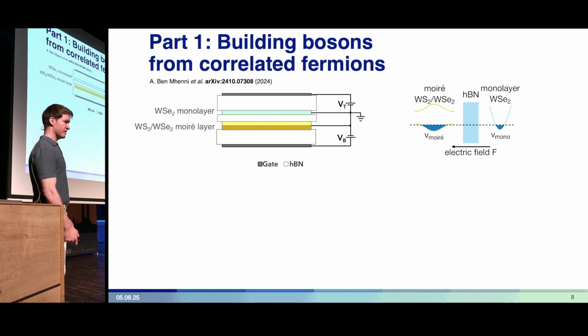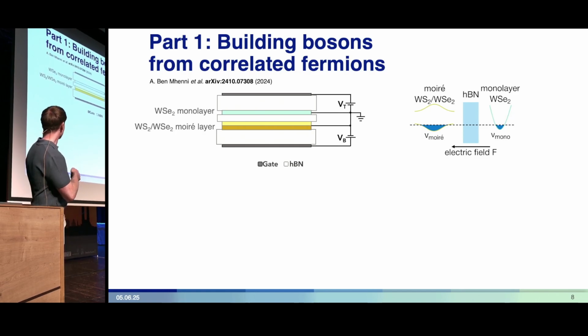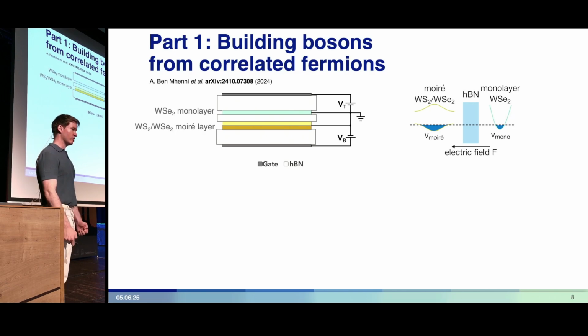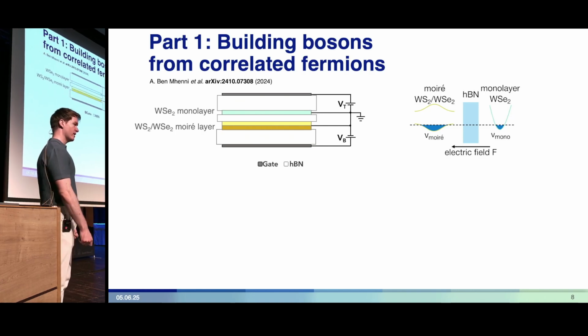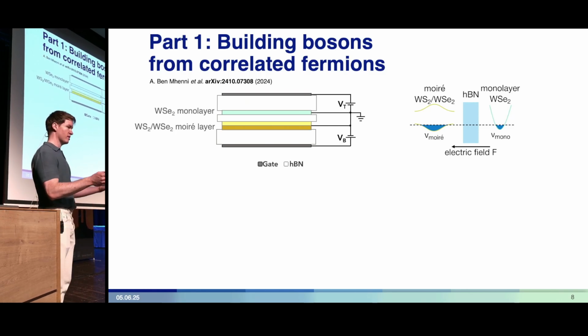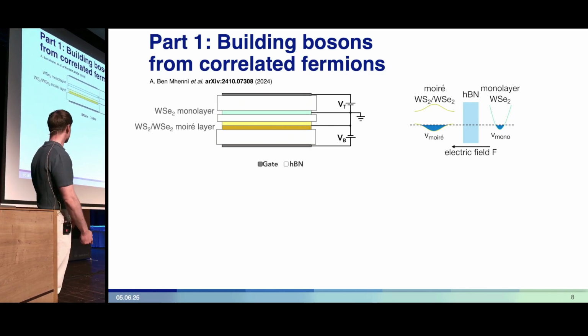Now I'd like to introduce the device that is part of the study. It's a bilayer electron system which consists of a monolayer of tungsten diselenide, separated from a Moiré heterobilayer consisting of WSe2 and WS2. They're separated by a thin layer of hexagonal boron nitride, a high-K dielectric that prevents tunneling between the layers, meaning the interactions between layers are pure electrostatic Coulomb interactions.